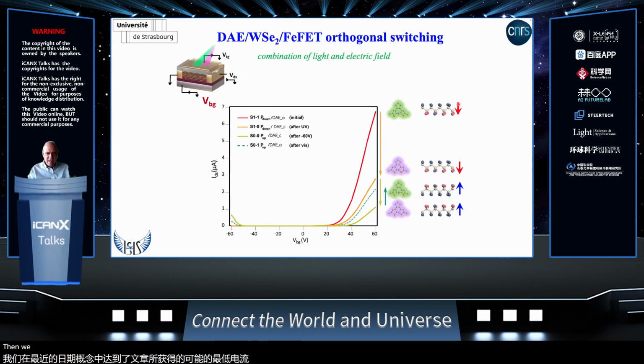Then we can irradiate with visible light in order to reopen the diarylethene, so untrap the photochemical, let's say, trapping. And in this way, we can recover partially the current in the channel. Then we can apply the 60 volt again. You can see that we can go back to the initial state with the highest current possible. So the current modulation is highly reversible, and